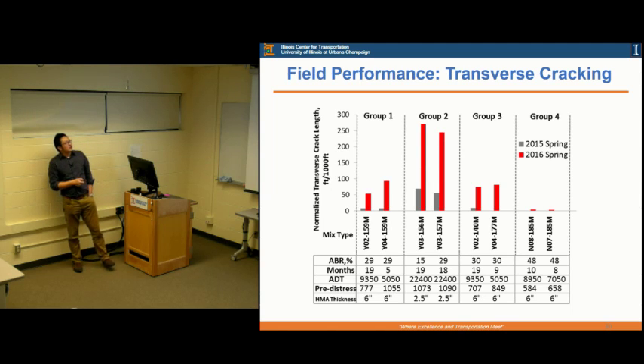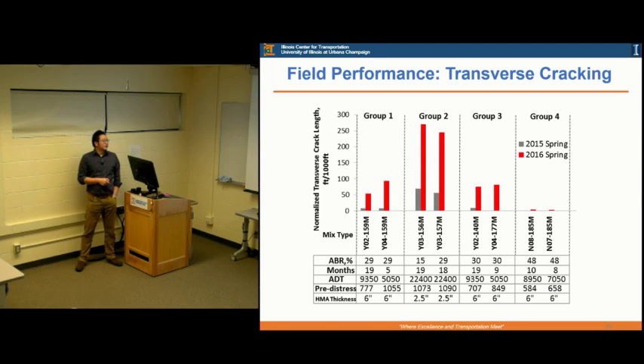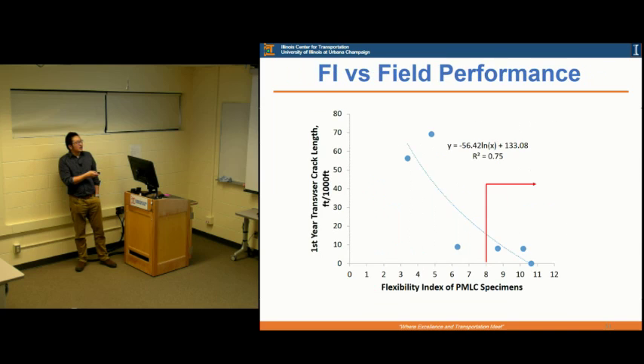But for transverse cracking, the field performance - there was a two-round survey, and for the first round there's just a little. But after the second winter, you see some mixes developed a lot of cracking. Why is that? Is it because of construction, mix property, or pavement structure? What we found is that it could be the mix problem.